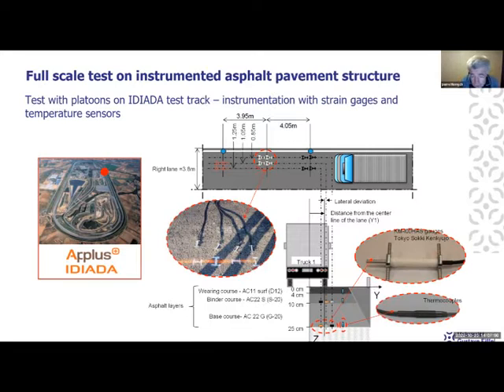So the pavement structure included, you see it at the bottom, 3 asphalt layers: a wearing course, a binder course, a base course. And we instrumented mainly the binder course and the base course. And we instrumented it with strain gauges and also with temperature sensors. So the objective was not to monitor rutting, but mainly to monitor the strains and then to evaluate fatigue of the pavement due to these strains. And so we had about, I think it's 30 strain gauges, which are placed longitudinally and transversally, so at 2 depths and also at different lateral positions, in order to capture also the effect of the wandering, the lateral deviation of the trucks.